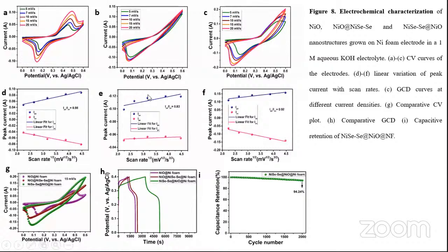Now, coming to the electrochemical characterization of the electrodes synthesized, figure A corresponds to the CV of the pure sample, and B and C correspond to that of the composite samples. Now, comparing the CV of all the three samples, what we found was that nickel selenide nanotubes grown over nickel oxide nanoflowers showed comparatively better properties than the other two electrodes. Similar kind of results were also reciprocated in terms of the GCD curve. And we also saw cyclic capacitance retention of around 94.24% even after 2000 charge discharge cycles.